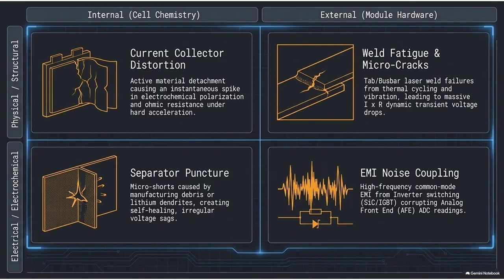Instead of safely embedding into the carbon structure of the anode, the lithium ions start piling up on the surface. They undergo a phase change, actually plating out as solid metallic lithium. Solid metal, that doesn't sound good. It's not. Over repeated cold charging sessions, this metallic plating grows outward, forming these sharp, microscopic stalactites.